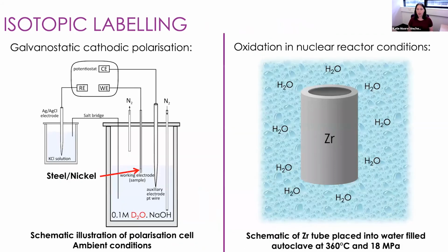So how do we get that deuterium into our alloys in order to be able to investigate its distribution? Well, we use slightly different approaches depending on the metal that we're interested in. And we do that to try and get as close as possible to in-service conditions. So for the steel and nickel alloys, what we do is we use galvanostatic cathodic polarization. So here we have our steel and nickel sample in a deuterated solution, and we are charging that sample in ambient conditions in order to push deuterium into that sample.